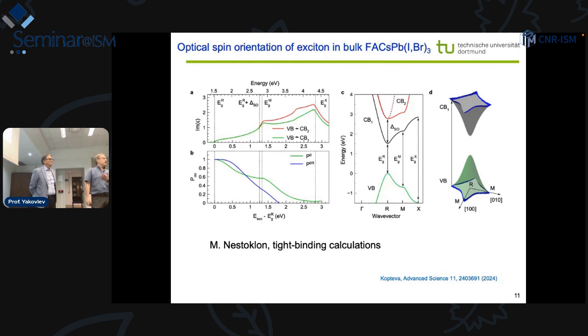For spin physics, what we see is that it doesn't matter whether you have cesium or organics. We didn't find strong contributions or strong differences between fully inorganic or organic semiconductors. It may be that we are working at low temperatures, where the rotational degrees of freedom of the organic molecules are frozen, so they do not appear. Otherwise, only the structural phase transitions, but it's more the size of the cation, as I understand. It's not so much whether it's organic or not organic.